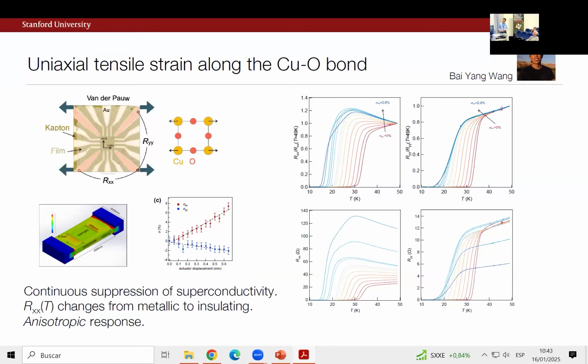So cool. Now he stretches this cuprate membrane. And what you see here in red is an unstrained state. It has a superconducting transition, as you'd expect. And now we're going to take this red trajectory. That is, we're going to probe the resistivity in the direction along that tensile strain. This is the raw data in the sense that you can see 2 things. TC is being suppressed, but also the normal state resistivity is going from metallic-like to insulating. So qualitatively not a surprise. I stretch this thing out, the overall scale of the resistivity is going up, and we also see TC being suppressed.